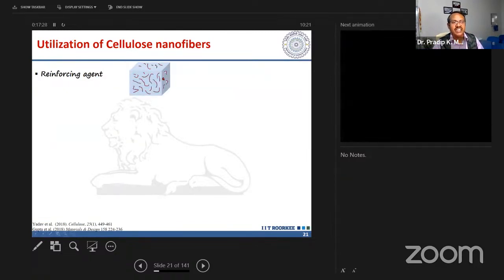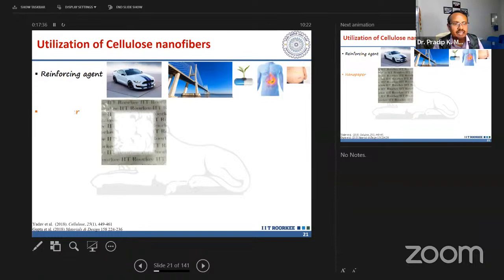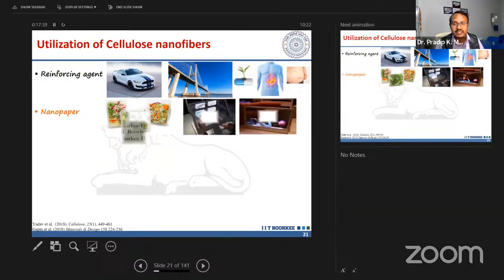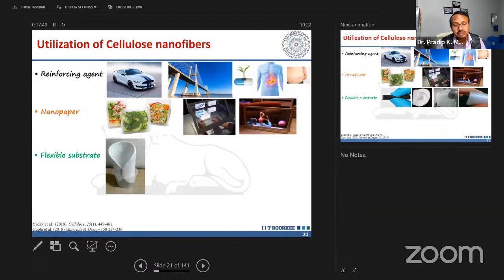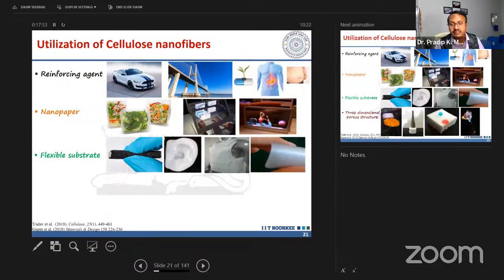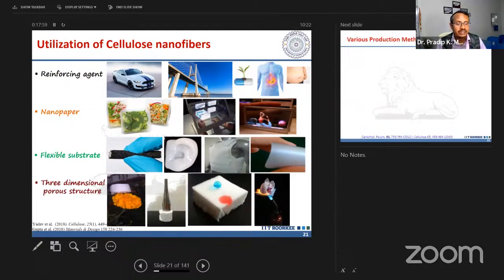So, different utilizations of cellulose nanofiber. As I told you, we can utilize it as cellulose nano reinforcement, and for biomedical applications also. We have developed nanopaper for packaging applications, and it can also be converted for display systems. We are working on cellulose nanofiber film for display applications too. Flexible substrates, as I told you, and cellulose aerogel we have already developed. It has very good mechanical properties and thermal insulation, and we can utilize it for different applications. It has a three-dimensional porous structure, so it is very high in strength, but its porosity is almost 98%. So we can utilize it for other applications such as oil-water separation. I will tell you about those slowly.